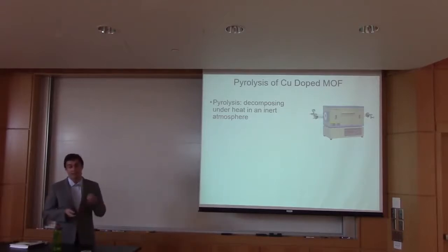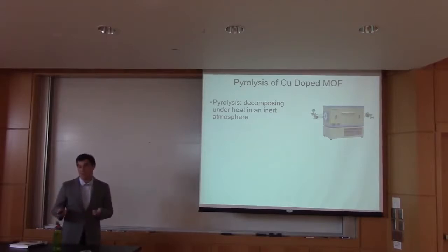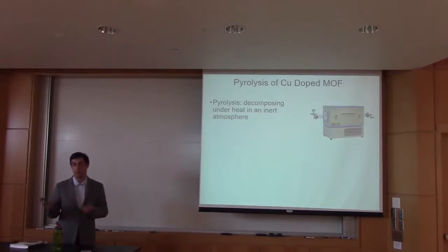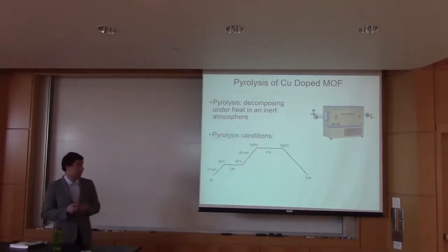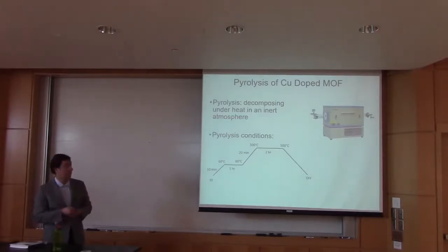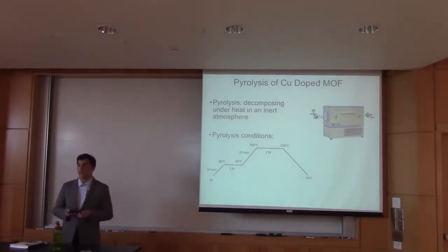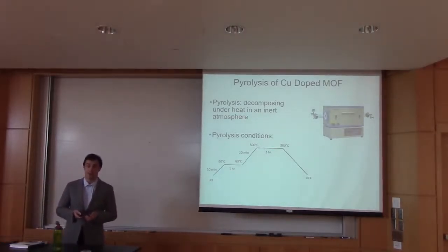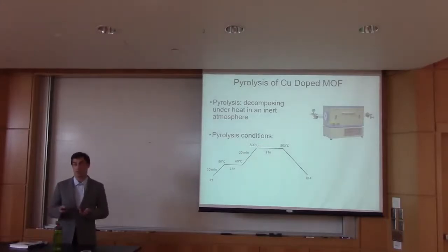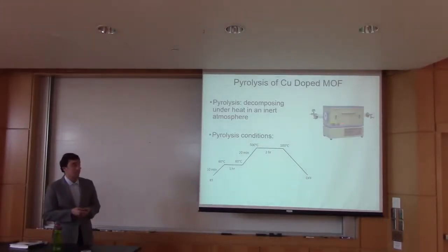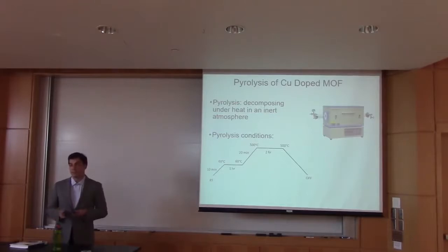You're heating it very hot, it's going to decompose, you're going to lose the organic units and be left with the metal bits. We're doing this in a tube furnace, which you can see here. It's a furnace that gets very hot, there's a tube running through it which is sealed to the atmosphere, and you can flow whatever gas you'd like through it and over your sample. We use nitrogen, and this is the heat ramp we used. The only really important part is this, where we're heating at 500 degrees Celsius for 2 hours. This might seem rather hot, but it's hot enough to decompose all of those organic units. And these furnaces can easily get to 1500 degrees Celsius, so all things considering, this is rather mild.